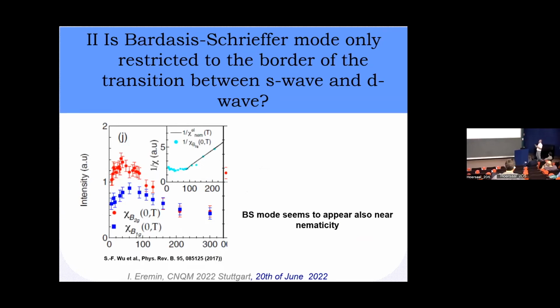there is of course a problem: you believe that you must be limited to the phase boundary between S and D wave superconductivity. And my answer is, wait a minute, because we actually know that in linear response experiments, when you probe what you believe is a Bardasis-Schrieffer mode in the superconducting channel, there is always some ambiguity. If you go to temperatures well below the superconducting temperature, and this is one of these systems, iron selenium, which I'm going to speak about in a minute, where the superconducting transition temperature is of the order of 10, 15 Kelvin, it actually turns out that the response in the B1g and B2g in the Raman